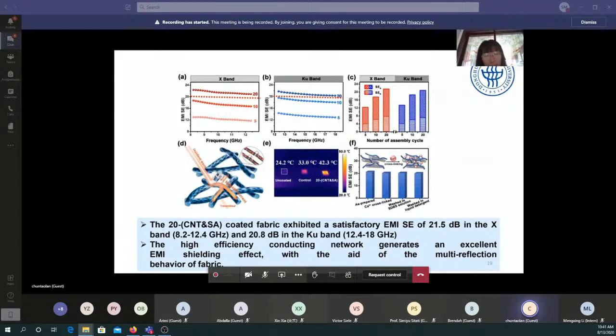This high-efficiency conductive network in the fabric generates an excellent EMI shielding effect with the aid of the multi-reflection behavior of the fabric, and this well-ordered coating interacts strongly with electromagnetic waves. And also, the fabric has good washing stability after the SA cross-linking. The stability shows the practicalness of the fabric.